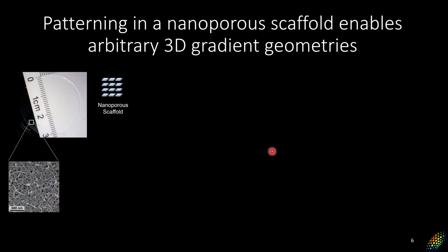Okay, so how does this work? The core process here and the core innovation on the material side is to pattern material inside of a nanoporous scaffold. When I talk about a nanoporous scaffold, this is what that looks like. This is a nanoporous silica material where, at the macro scale, it looks like a very transparent, kind of dull piece of glass. But if you zoom into the nanoscale, you have this highly porous nanostructure that's very sponge-like. This is typically about 80 to 90% air.